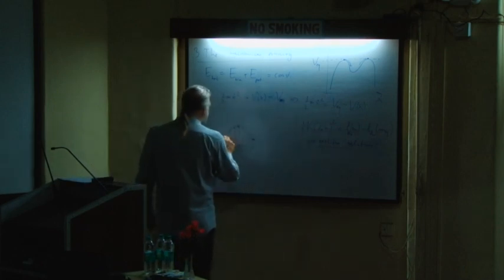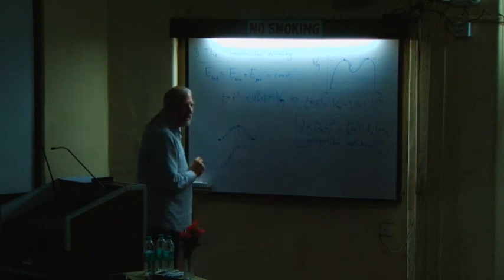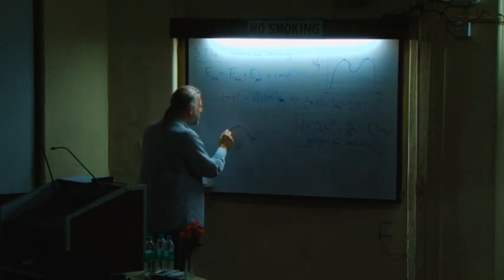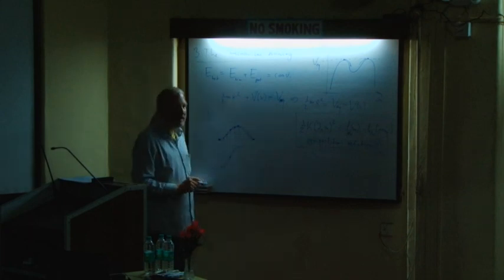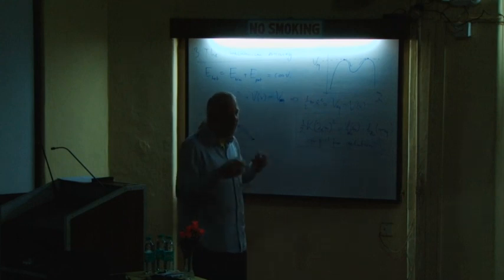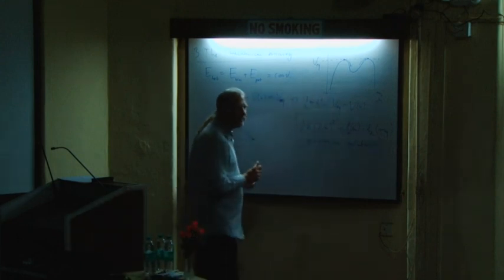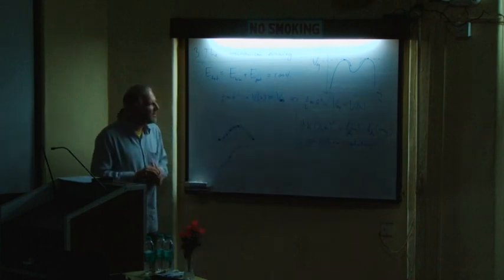So it has to sort of go over that hill. That is, we have some space points where the free energy is higher than in the equilibrium states. So that means this domain wall solution will have a higher energy than the homogeneous phase. Okay, and that's the origin of the surface free energy.